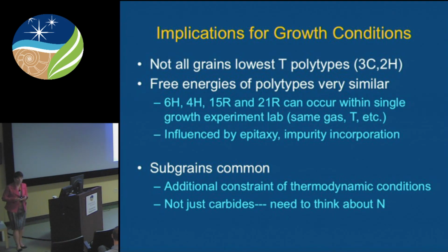All right, so what does this mean for the condensation environments, the stars in which these grains are produced? Well, we've learned from this study that not all grains have the lowest temperature polymorphs. It's not all 3C, 2H, and the intergrowth of those two particular phases. And this isn't entirely surprising. The free energy differences between the polytypes of silicon carbide are actually really small, and in a laboratory experiment with the same pressure and temperature, you get coexistence, co-formation of all four of these polymorphs.